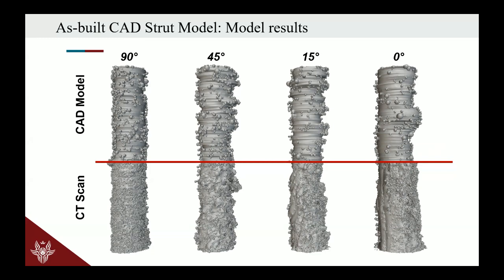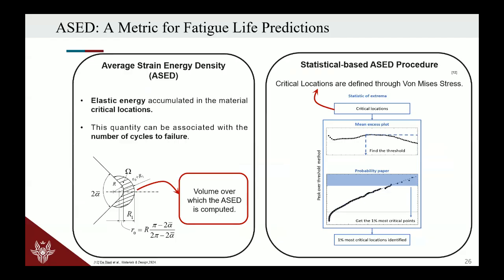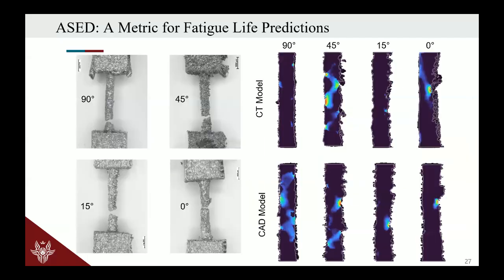After that, we also went to the life prediction or fatigue life prediction of this structure. And also here I will be quite brief, but we proposed the strain energy density that is quite efficient because, as I mentioned before, it's not sensitive to the refinement of the mesh, and the results are quite accurate also with coarse meshes. And so, first of all, we evaluated if with the CT scan model and with the CAD model we were able to check and find the real initiation point for the fatigue failure in this kind of structure, and actually it works.